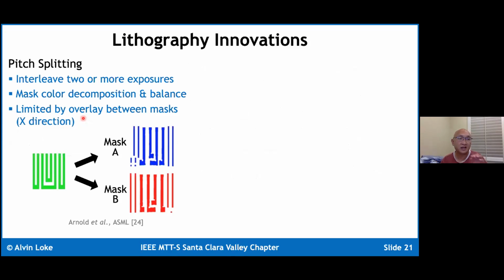Obviously you would print essentially alternating features with one mask, and then every other alternating feature with the other mask. Now, when you're doing this with different masks, you're obviously going to be prone to overlay or misalignment between these masks. So if you misalign, for instance, mask A and B in the X direction, you could inadvertently end up with a space that's too tight and cause shorts in the desired feature.